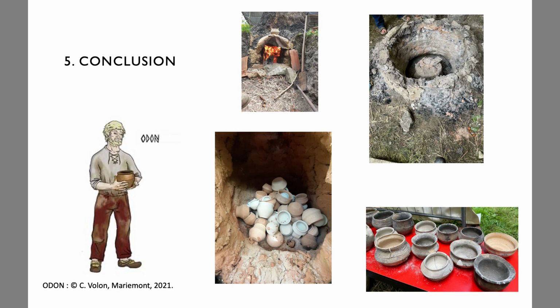In conclusion, the kiln of Kevi was easy to build, but it was much more unpredictable during the firing. On the opposite, the building of the kiln of Namur needed more time, people, and material, but it was very efficient during the firing. The kiln of Namur is in the tradition of the Roman kilns, but the one of Kevi appears as a new solution, perhaps even a trial, which required less work for its construction, but needed a great mastery of the firing process.